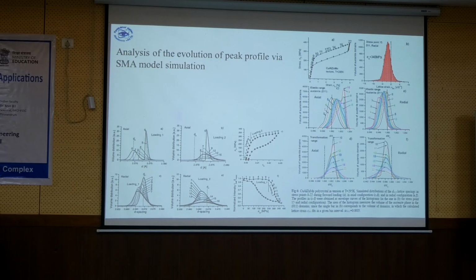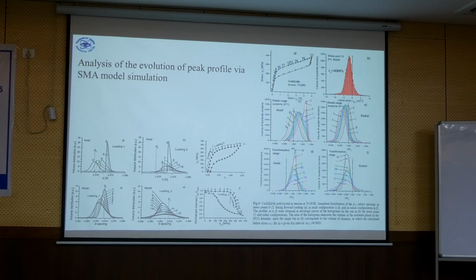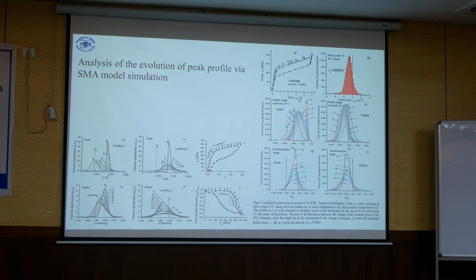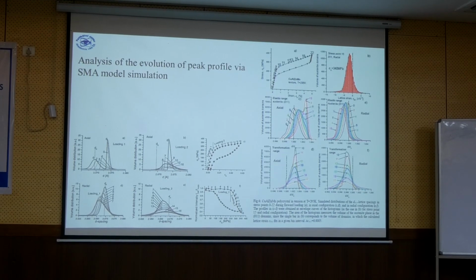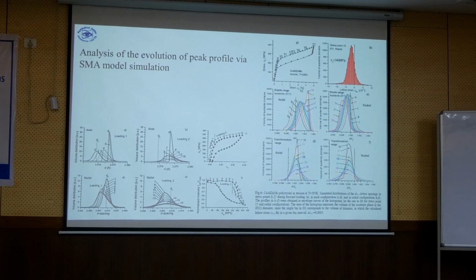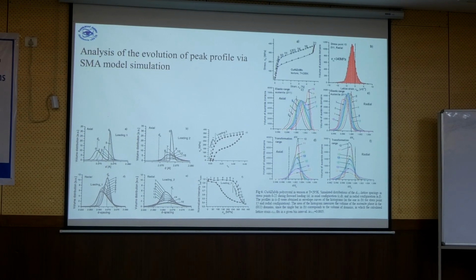Because the volume increases, if it becomes too narrow, it has to be wider. The intensity is not decreasing so much. In the beginning, because of this break, and the break means that in some grains it cannot shift further. So this is one cycle we are talking about, only the one part where we do different sections.